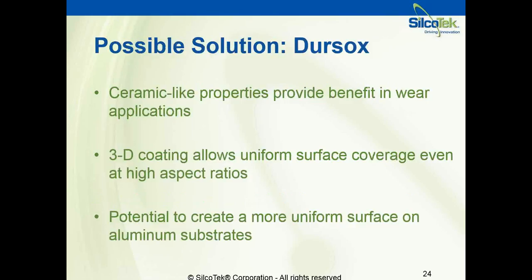Our Dursox coating is the one that we offer that will mitigate the erosion issues. The layer is a silicon oxide plus some embedded carbon, which adds a ceramic-like strength. So it has a lot of benefit in wear applications and erosive applications. Of course, the nature of the CVD process being a three-dimensional coating under vacuum allows the surface to be completely and uniformly covered even with high aspect ratios.